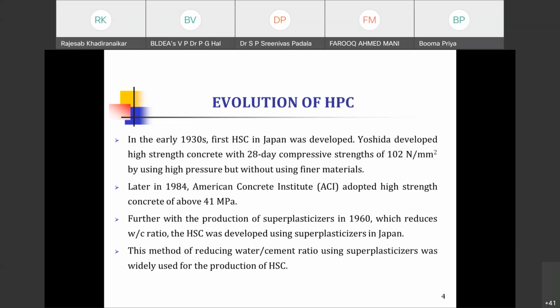In the 1930s, the first high strength concrete in Japan was developed. Yoshida developed high strength concrete with a 28 days compressive strength of 102 Newton per millimeter square by using a high pressure, but without using a finer material. So earlier it was application of pressure that resulted in the high strength because they were not much aware of the microstructure. They were only bothered about the macrostructure, and if high pressure is applied, then naturally the voids will come down and there will be increase in strength. That was the concept.